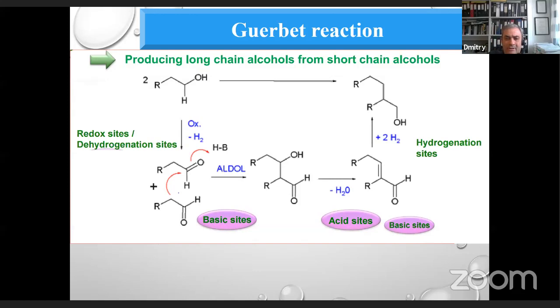In connection with biomass transformation, it's interesting to consider a somewhat more complicated reaction, which also comprises aldol condensation. In principle, we can start not only with aldehydes, but also with alcohols. Then the first step will be dehydrogenation on, for instance, metal sites, producing an aldehyde, then aldol condensation on basic sites. Then we have a dehydration reaction requiring either basic or acid sites, and then hydrogenation.